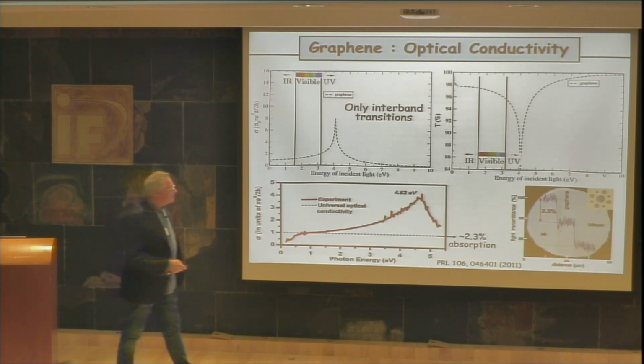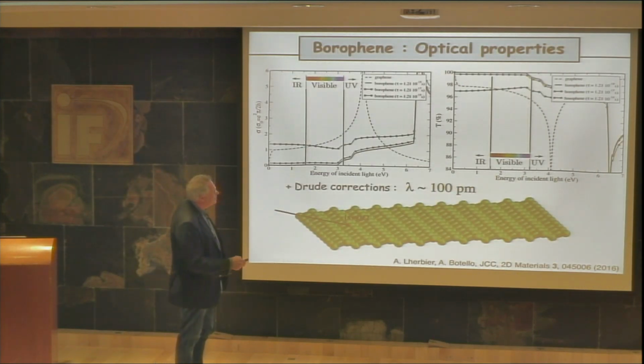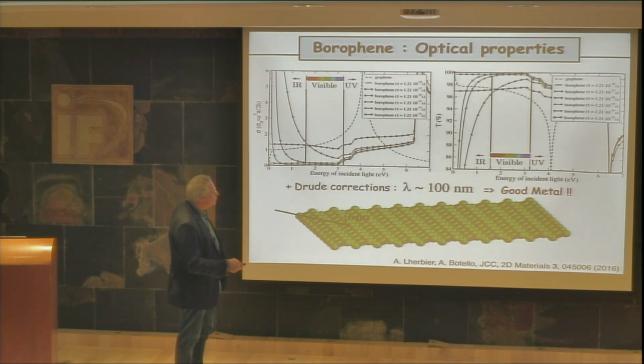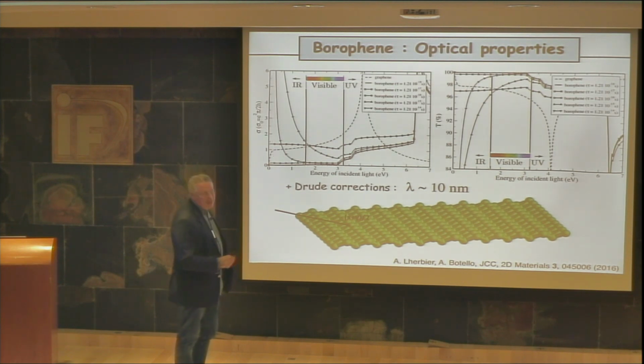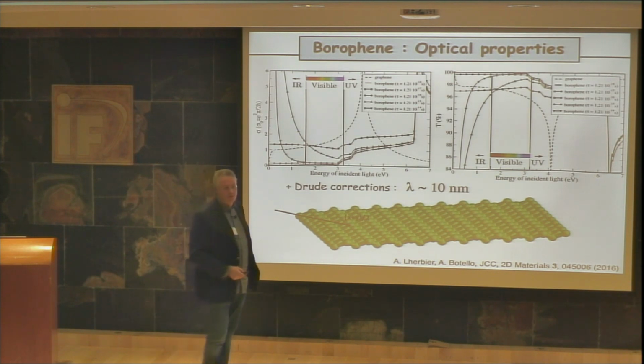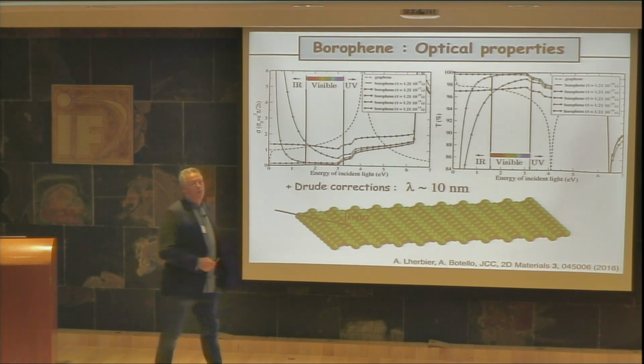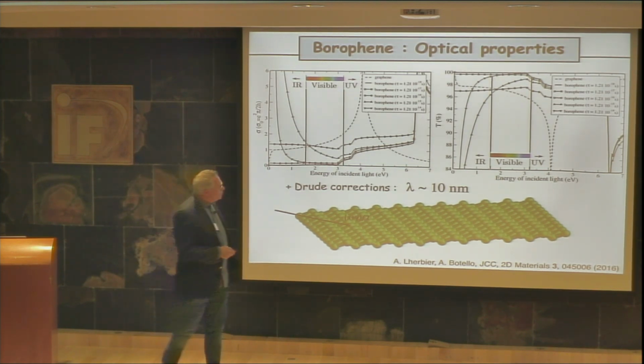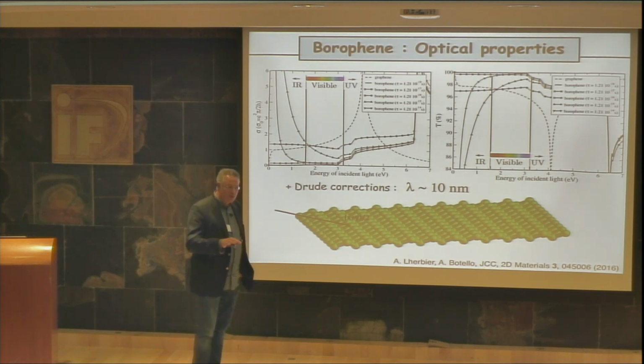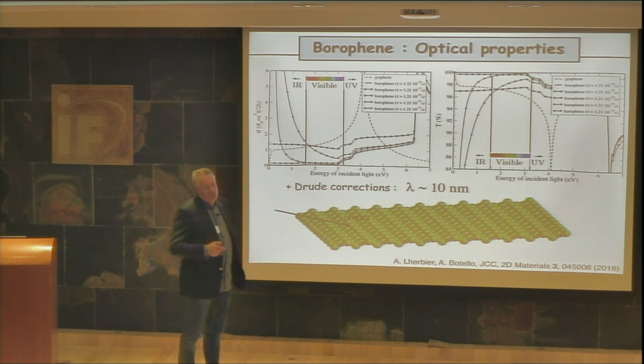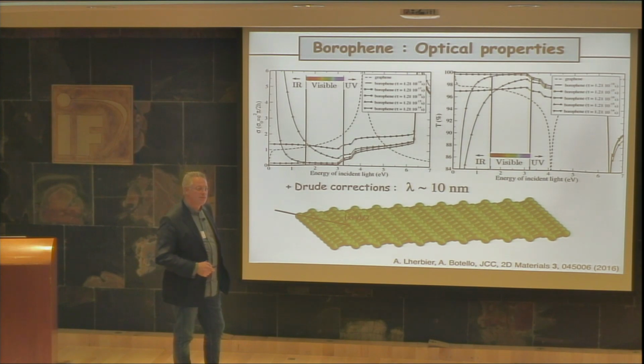But let's say that for a metal, between 10 and 100 nanometers, you do not see much difference in the transmission. Even if you have only 10 nanometers for the electronic mean-free path in your borophene material, you'll still get close to 100% transmission. So it's not going to play a real key role in the transparency of borophene. We checked that just to be sure that we were not wrong, by looking only at the interband transition in the dielectric function. But in fact, it does not play a key role in this system.